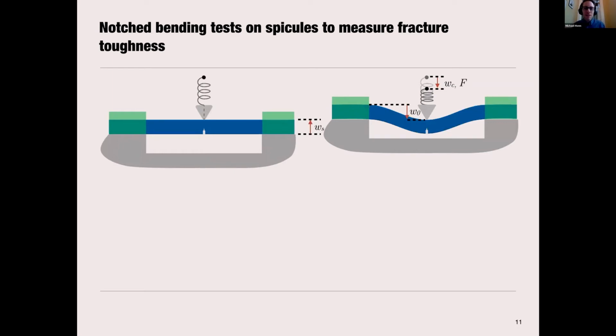You'll see the configuration that I've shown here is a little bit different from a standard 3-point bending test. You have the specimen shown in blue, the stage shown in gray, and the edges of the specimen over the stage have this green shade to them. And that's glue that we have applied to the edges of the specimen. So we've glued the specimen down so that it isn't a 3-point bend test, it's kind of a double encastered 3-point bend test.